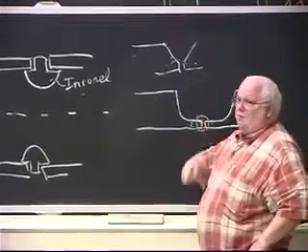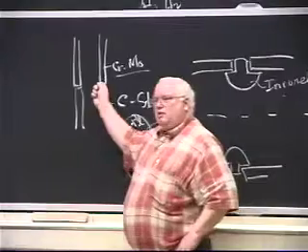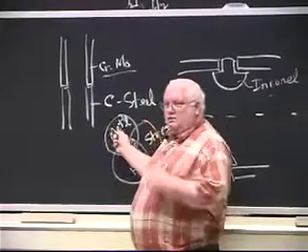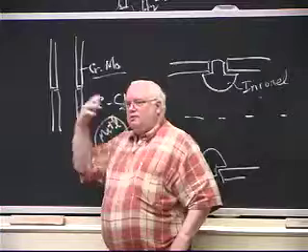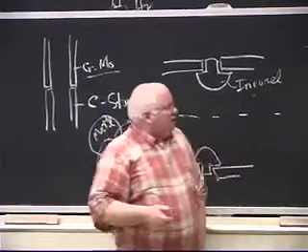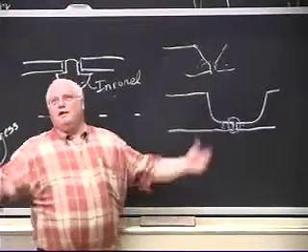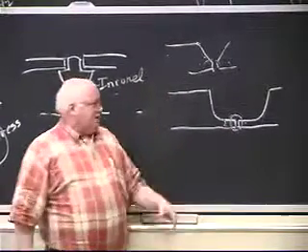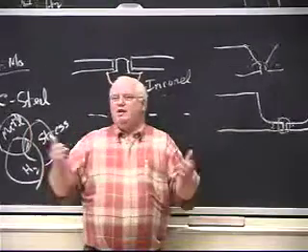Then you have to wrap it in a blanket because this chrome moly steel has to cool very slowly, or you'll get a very high hardness, which increases the hydrogen cracking propensity. And so you wrap it, you thermally insulate it. At that time it was probably an asbestos blanket. Anyway, and you wait 30 minutes. And the whole time, every 2 minutes, "This is not going to work, this is not going to work." So we wait 30 minutes, take the blanket off.